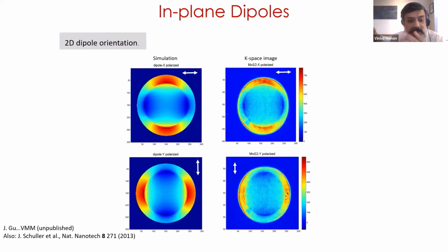So the other interesting property of these materials is the fact that all the excitons lie in the plane. This is data from photoluminescence, where we've just imaged it in the Fourier plane, and you can see that the emission radiation pattern closely follows what one would predict for a two-dimensional dipole.